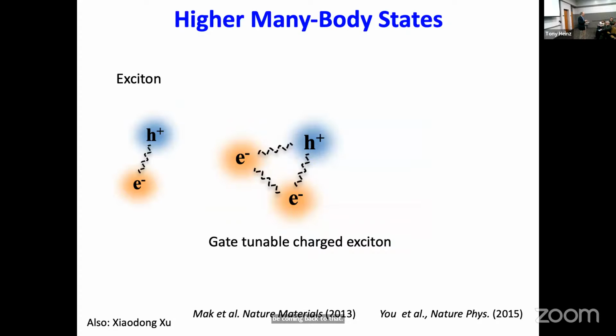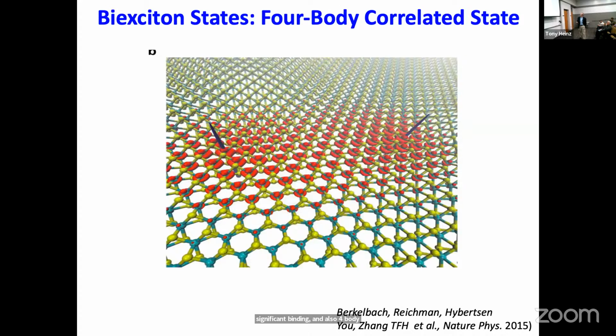One of the marvelous things about 2D materials is all the ways you can access them and tune them and modify them. One of the simplest things is to add more charges by a gating effect. So if you put an electrical contact on the 2D material and you change the potential with respect to the substrate, you change the charge density. And one then immediately saw signatures of these 3-body excitonic states. So this would be like the hydrogen anion, which also had a fairly significant binding, and also 4-body biexcitonic states. And this is the corresponding representation of the wave function.